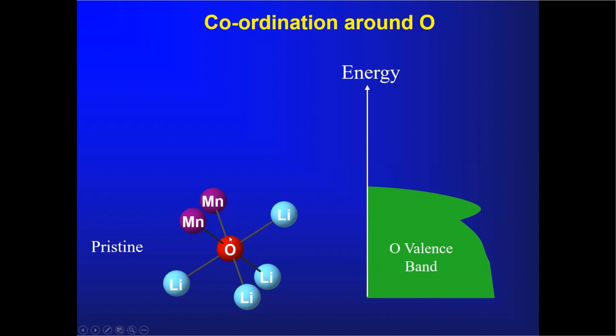And if we focus on this dumbbell arrangement here, this means that the oxygen 2p state here has only very weak covalent interactions, in other words, it's only got principally ionic interactions with lithium. And what this basically means is that these oxygen 2p states associated with this configuration will tend to sit at the top of the oxygen valence band represented by this red region here. So one finds in DFT that the highest energy filled oxygen states tend to have a lot of character from these interactions here.